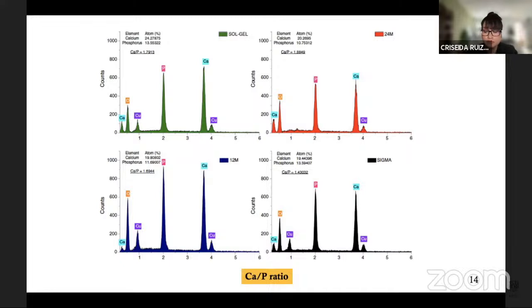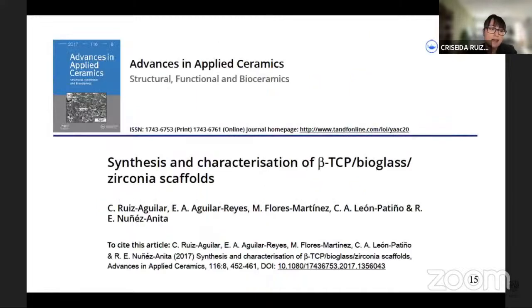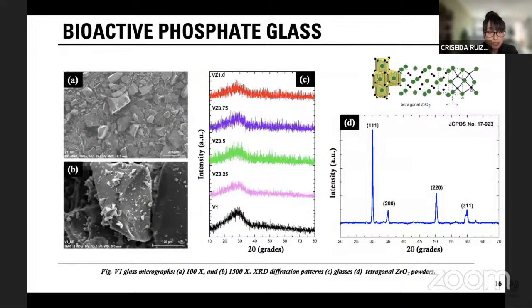This data indicates the calcium phosphate phases, which allows us to analyze and understand the dissolution of the powders in contact with body fluids. Some studies have presented bioactive glasses doped with different elements and improved mechanical properties or reduced the dissolution process. Nevertheless, several compositions of bioactive glasses doped with zirconia or zirconium oxide were manufactured to improve the dissolution properties and the cell interaction in this investigation.